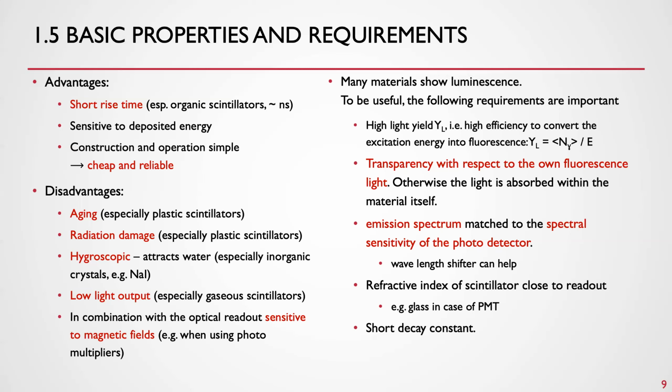Lead tungstate, the crystal scintillator, is actually radiation hard until it hits, it's fairly radiation hard, but it has limitations. The lead tungstate crystals in the CMS calorimetry for the sector that's closest to the beam pipe have lost more than 98% of their signal yield. So it's already down to 2% and will therefore be replaced for the high luminosity upgrade in a few years.